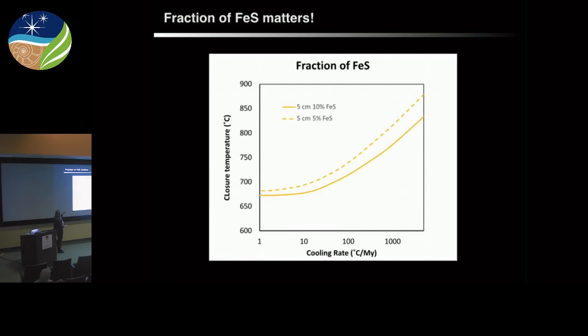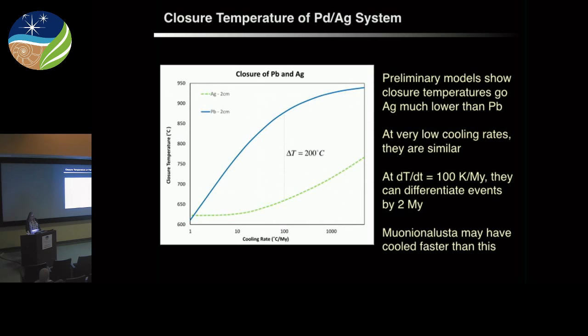So here's two examples that can differ, not a huge amount, probably not even resolvable compared to the ages that we're measuring, but it is an effect on the order of 50 to 100 degrees, depending on the amount of troilite in your sample and how far apart each of these are from each other. Okay, finally, we can just talk for a few minutes about using these two things in conjunction with each other.